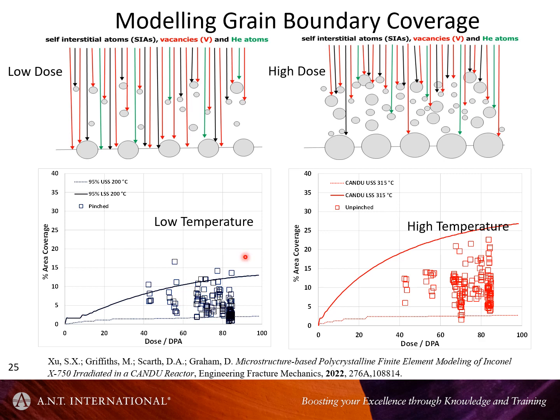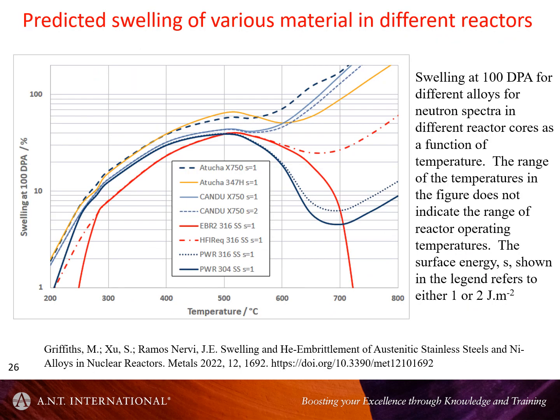And ultimately, the principle is that you're always getting point defects of all types to the boundaries, and at low doses, there's not many bubbles in the matrix because you don't have enough helium generated to interact with this flux of point defects. And at high doses, this shuts down. So the good news is that from a point of view of the modeling, and from the point of view of the reactor operators, the rate is dropping with increasing time. So the modeling at least shows that it's not going to be an accelerating effect.